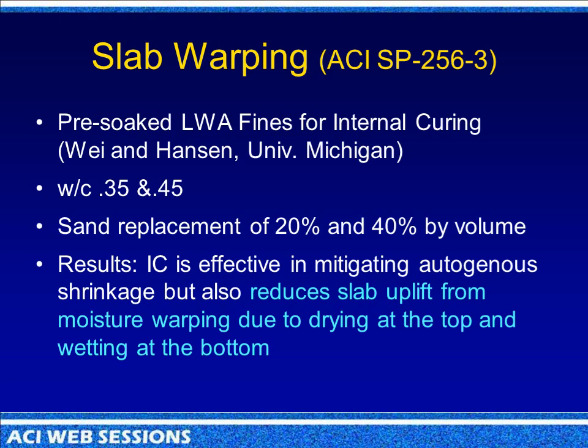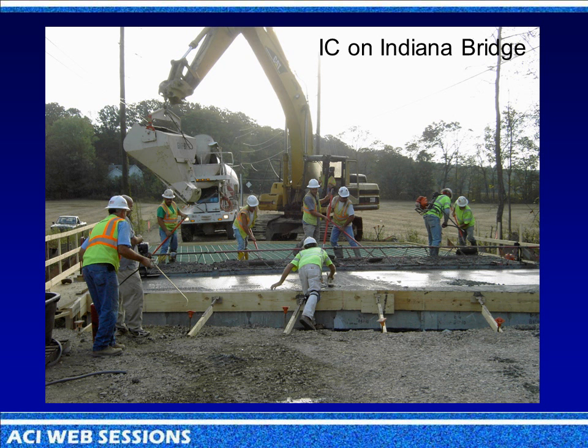Slab warping, they did some studies here, and here's what's very interesting. They said it reduces the slab uplift from moisture warping due to the drying at the top and wetting at the bottom. So they've even noticed that it can help you here with warping. And here's a project going down. It's a real test project on a bridge.